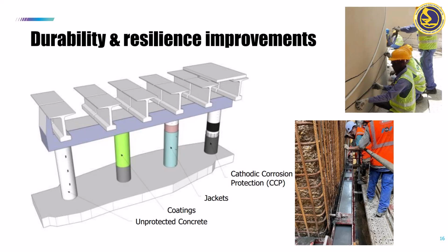and one that I will focus on a little bit more on the next slide is ultra high performance fiber reinforced cementitious products, or UHPFRCs, UHPCs like people call it, which are extremely dense and almost watertight cementitious material with a high concentration of short steel fibers, and therefore able to bridge cracks, and actually with quite a significant tensile capacity. So using this as an overlay allows you to do this type of durability repair, like you see at the bottom right, which is actually a pylon of a cable-stayed bridge that suffered alkali sulfate and alkali aggregate reaction,